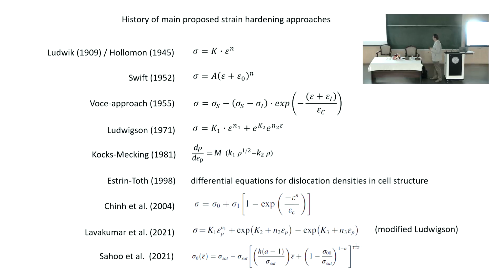A recent phenomenological fitting function is Chinh et al. It's a little bit similar to Voce, a modification of the Voce approach. You find the same elements in it, except there is an n parameter on the strain. It was proposed in 2004 and works quite fine, with a reasonable number of parameters: one, two, three, four.